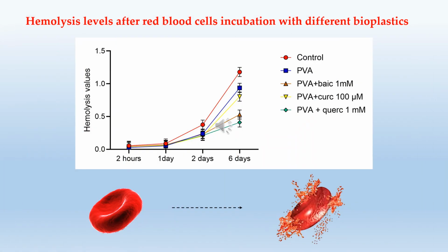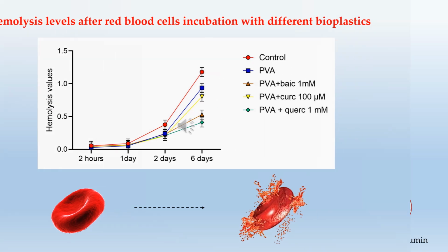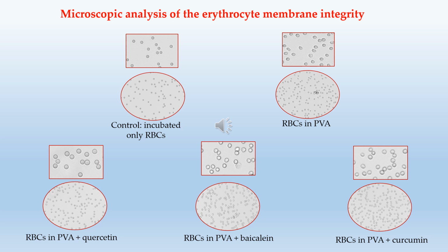The results obtained after incubation of the polyphenol functionalized biopolymer with red blood cells show a reduction in the rate of hemolysis up to 6 days of incubation compared to the control in all the bioplastics with polyphenol, and in particular in the presence of quercetin and baicalein. These data were confirmed by the morphological analysis of the cells, which shows a better membrane structure in RBCs incubated with bioplastics containing PVA functionalized with polyphenol compared to control.